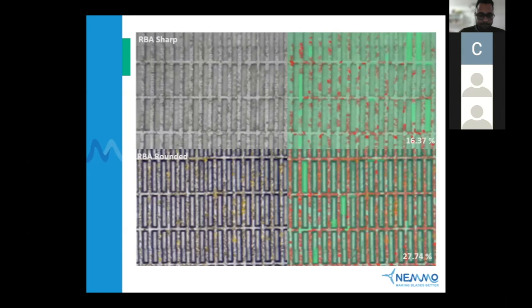Looking at the surface microtextures, the clustering of cells between uniform gaps of adjacent features appears reduced. If minor clustering of cells does occur, it tends to be at the ends of the features rather than in between adjacent features. It was also noted that the size of the organisms attaching to the microtextures are smaller than that which would be observed on the glass.